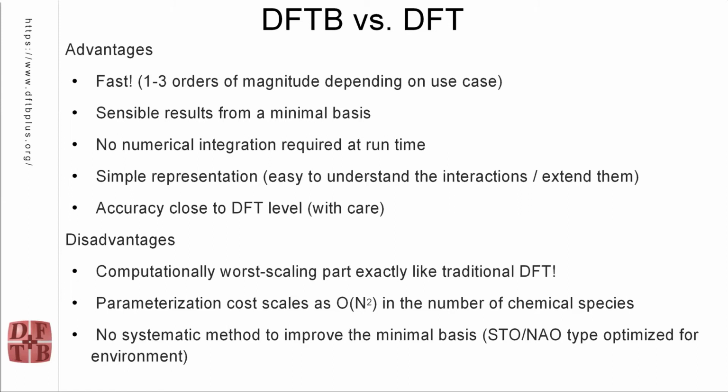Okay, so you get a sensible answer from a minimal basis calculation, and the thing clearly breaks its calculation down into different types of interactions. So for example, you can talk about the energy of atoms within a molecule or a larger structure. I've seen this be used to advantage to, for example, look at energies around dislocations in crystals, because you can resolve the local strain and local energies onto the individual atoms in the dislocation core region and talk about this. And you can get accuracy close to DFT level if you're careful about it.